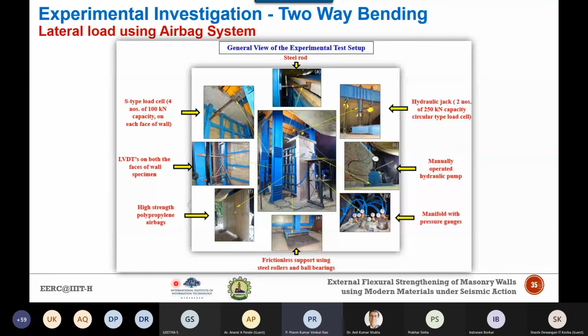To distribute the vertical load uniformly in the test wall, a steel beam has been attached to the top of the RCC wall along the length of the main wall. The lateral load has been applied using S-type load cells, attached between the backing frame and the reaction frame at the 4 reaction points. The displacements have been measured using 4 LVDTs: 2 LVDTs at the front side of the wall and 2 LVDTs on the other 2 ends of the wall. To minimize the friction underneath the backing frame of the applied load, the backing frame has been supported on rollers and ball bearings. And the lateral load, the most important part, has been applied by using these airbags.